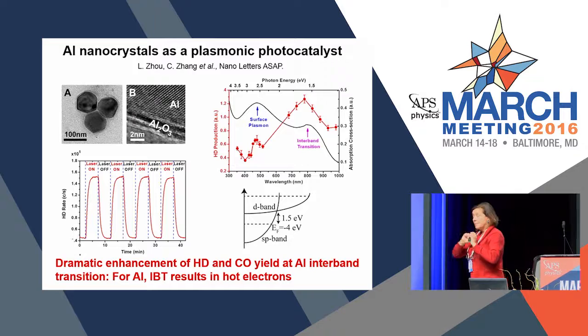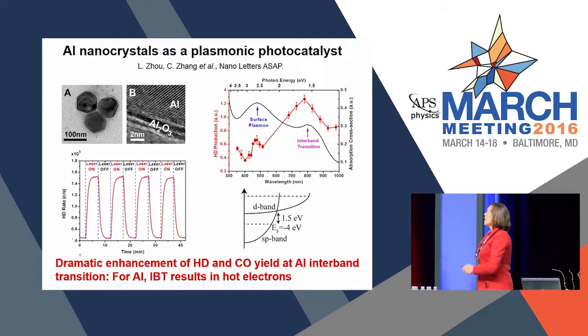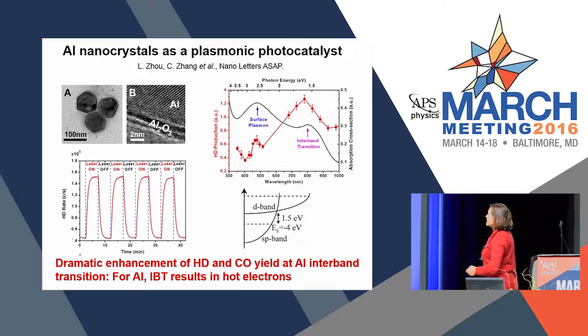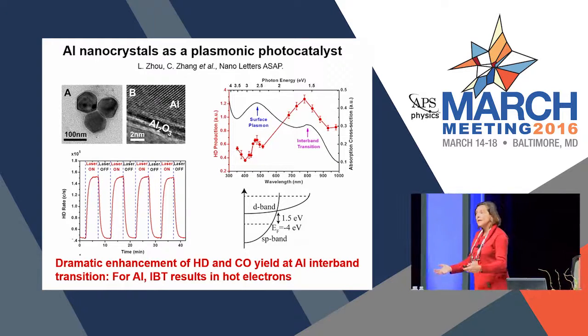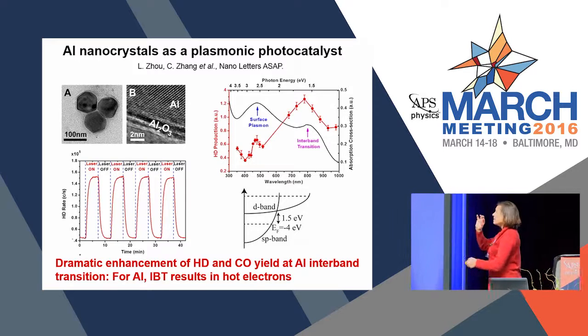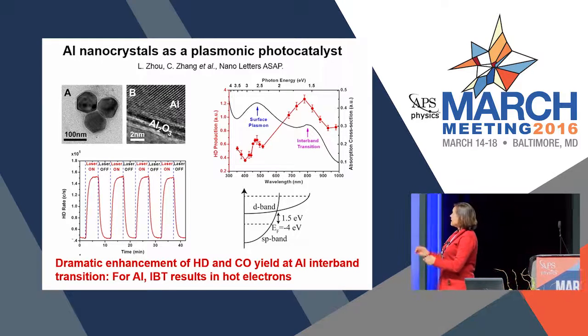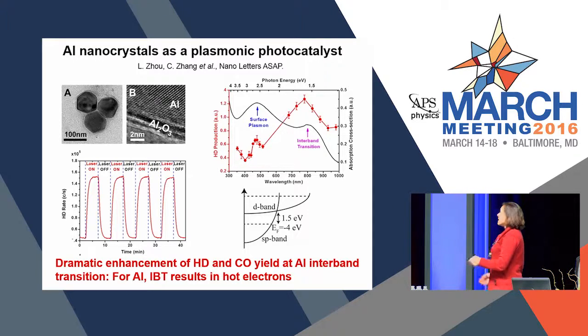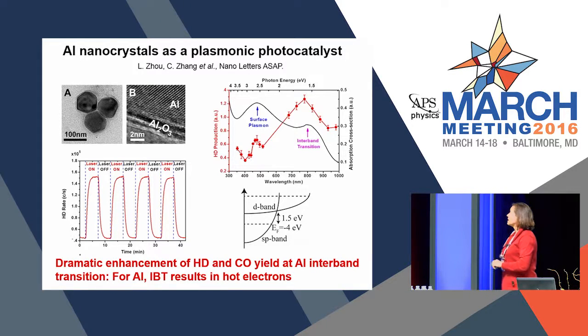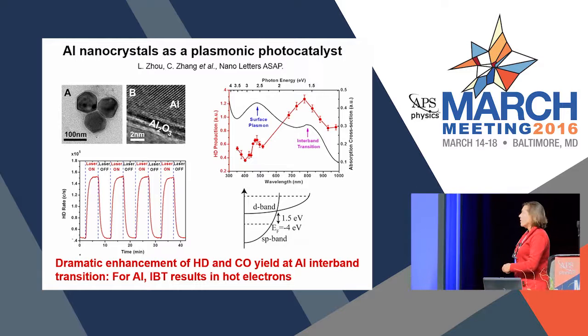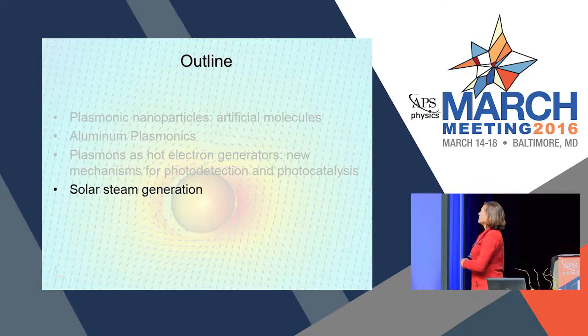Can we also take H2 and D2 and shine light using aluminum nanocrystals and obtain a similar type of result? And yes, they are just as catalytic as the noble metal, but with a slight change, and that is that the electronic structure is quite different from aluminum. In aluminum, you have a D band below the Fermi energy, and that actually results in a high density of hot electrons at an interband transition that's at lower energies. And it turns out that the interband transition, more than the plasmon energy, as you can see in the spectrum here, gives rise to the most hydrogen dissociation.